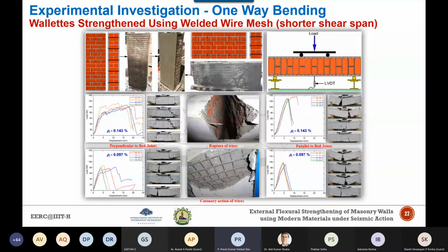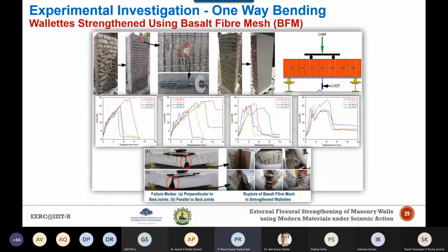Now let's come to the basalt fiber mesh. As I said, in case of the wire mesh, a similar technique was applied. Here also we applied the first layer of plaster, then laid the basalt fiber mesh, and then the second layer of plaster was applied. And here, rather than dowel bar, mechanical anchorages or mechanical wall plugs have been used to join the masonry substrate and the strengthening reinforcement. And we tested in a 4-point bending test.